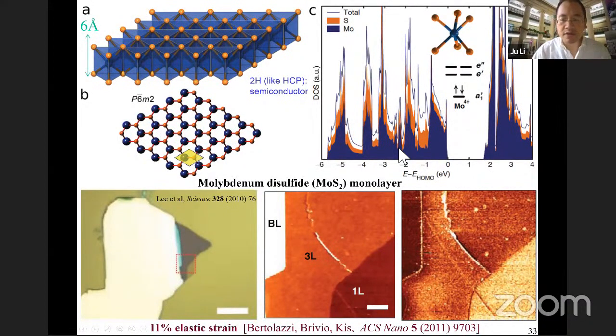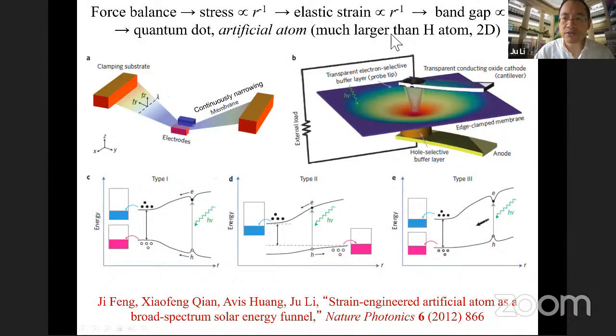So I would like to first talk about this molybdenum disulfide monolayer material, because people have already shown at room temperature they can sustain 11% tensile elastic strain indefinitely. What we thought back in 2012 is, imagine you have this monolayer and you make a triangle so that the cross-section reduces as the distance to the origin, so it goes as R. Now, if you pull in the center, the total force is a constant. But that means that the stress would be diverging as 1 over R, and that means the elastic strain would go as 1 over R. Toward the origin, it's going to be higher and higher tensile strain. And then you would have a band gap, which would also shift as 1 over R.